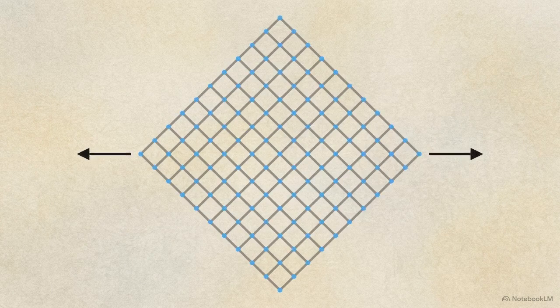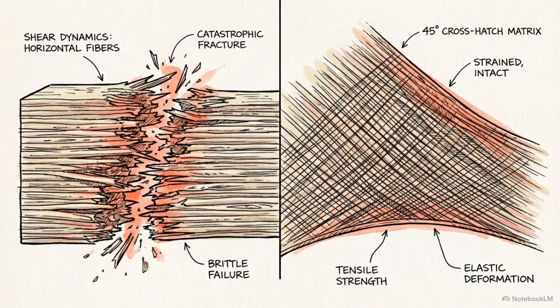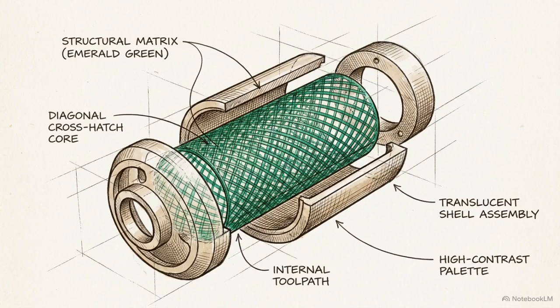When a tensile load is applied, the alternating cross-hatched layers facilitate controlled shear deformation. The matrix absorbs the energy, allowing the individual layers to slide and stretch slightly across the print volume. A 90-degree orientation locks the fibers in place, resulting in a rigid, brittle failure. The alternating layers distribute the strain. Ductility in 3D printed parts is an engineered mechanical feature. We force the toolpath to absorb energy through internal shear dynamics.